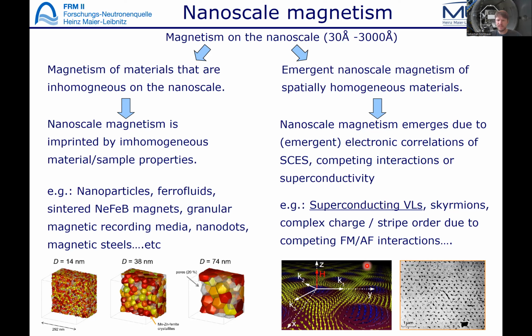We see that here on the bottom right, we have these very nice and very old decoration images of the superconducting vortex lattice, seen here on the surface of a niobium sample, where you see the hexagonal pattern of the vortex lattice. And this is what I'm going to briefly introduce in the next slides.